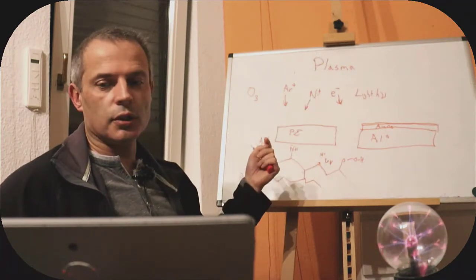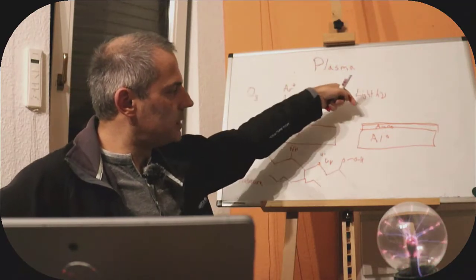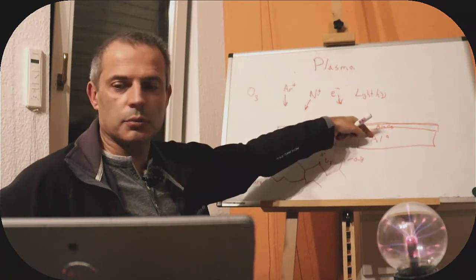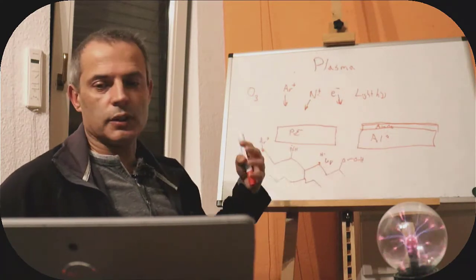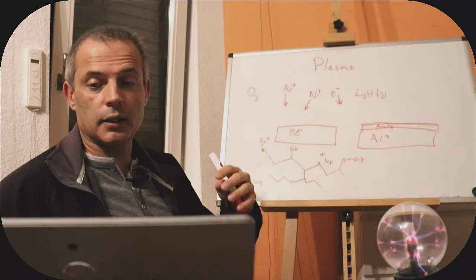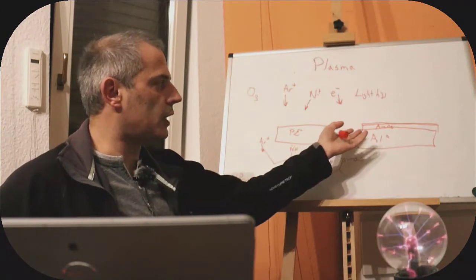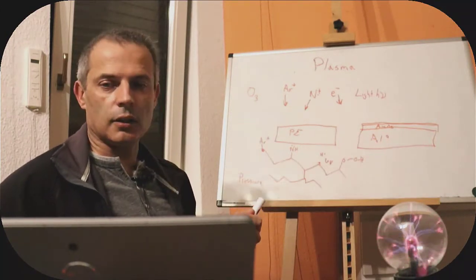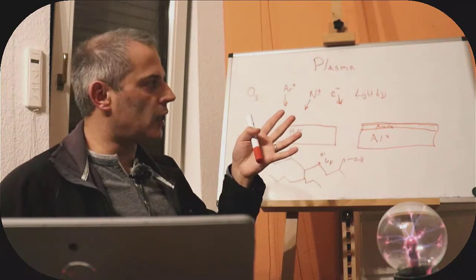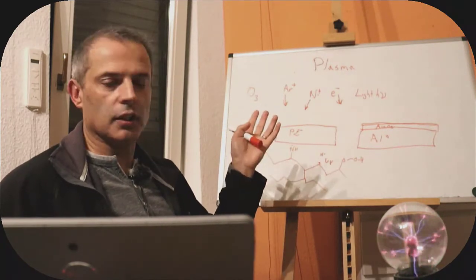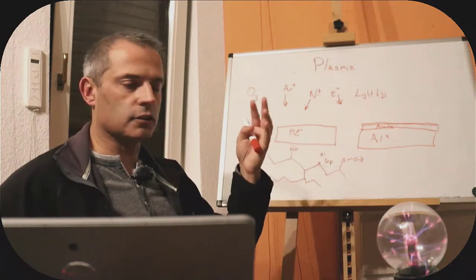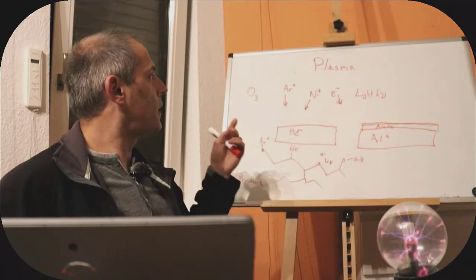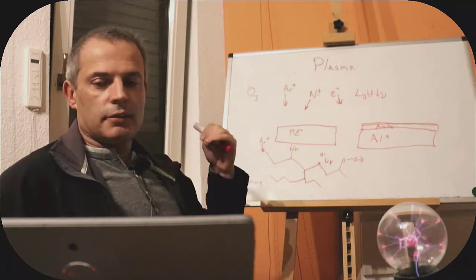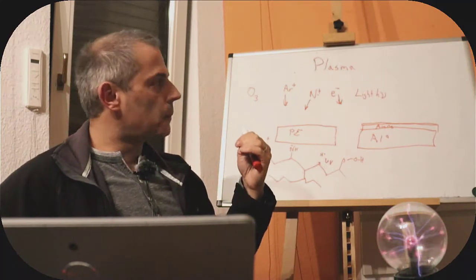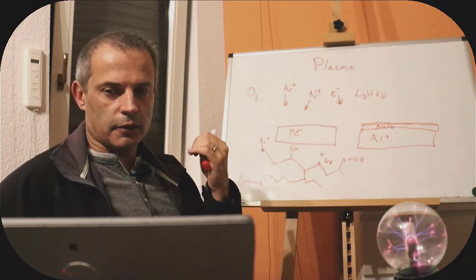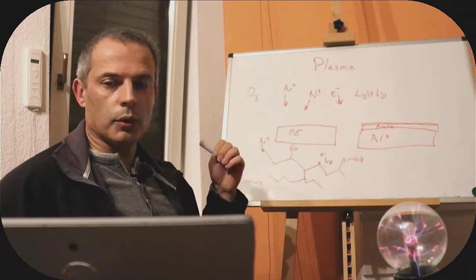If we have nitrogen ions, we can shoot those in through the aluminium oxide and sometimes implant them into the metal, which will interfere with its crystal structure and maybe make something new. It might make aluminium nitride, or if it's in metals, it might just implant ions below the surface, which change the hardness of the surface layer. So we get different effects depending on what our substrate is. And we might want different effects depending on what we want to do with it.